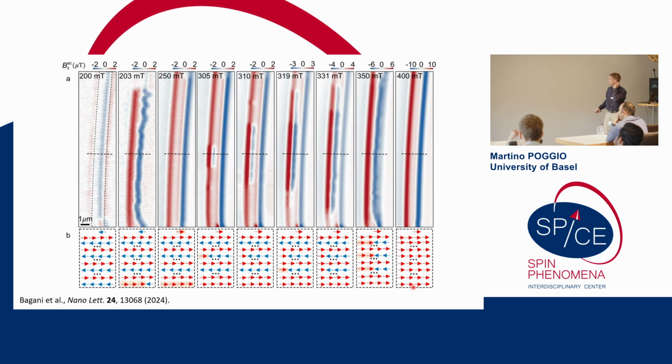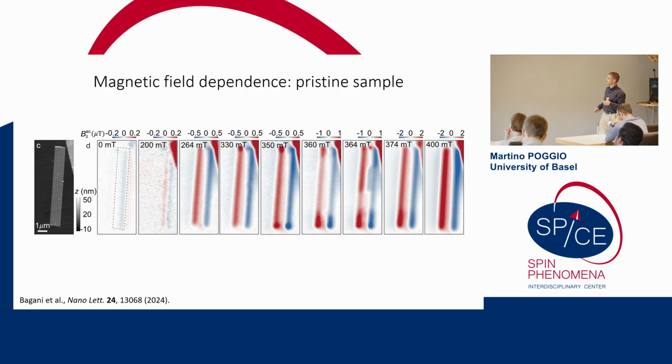To understand this, let's say at least from a cartoon point of view, you can see here what's going on. What we know in this part here is that the bottom layer flips first, because from our measurements of the stray field of this top layer, we know the orientation of the top layer, and we know that either the top layer or the bottom layer should flip first, because those are the ones where it's more energetically favorable. And then after that, we have no idea which internal layers are flipping, because they all look the same to us from the outside.